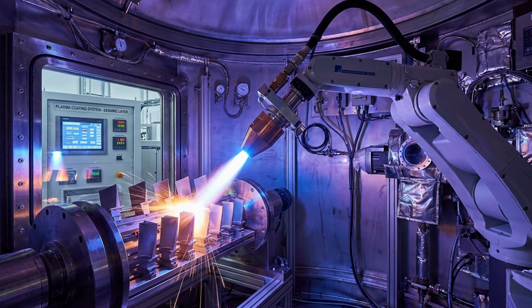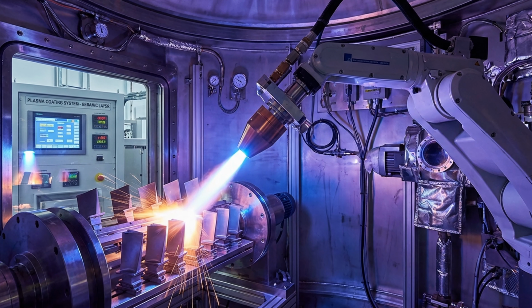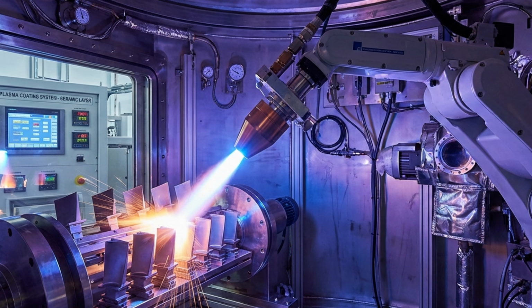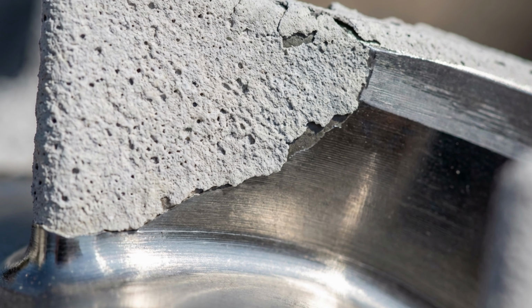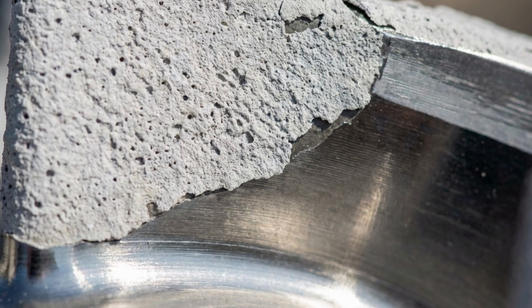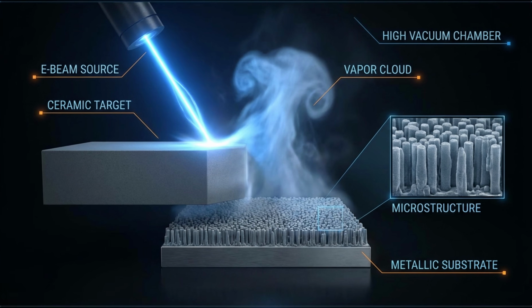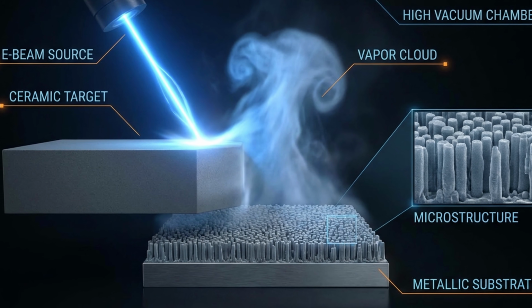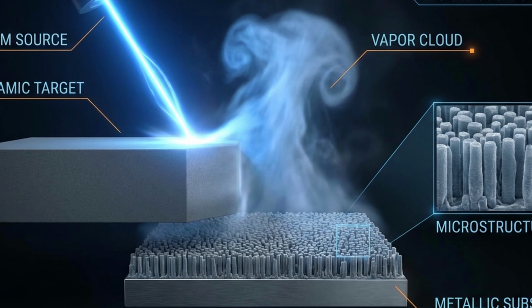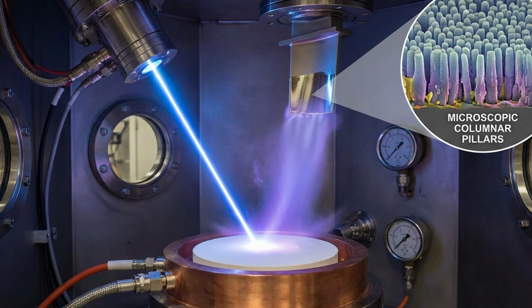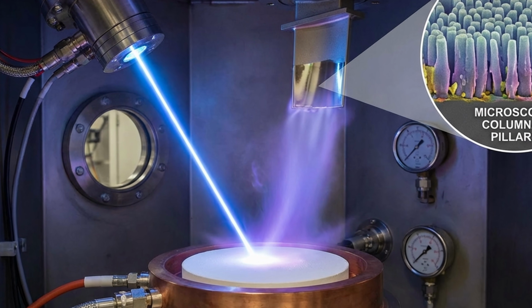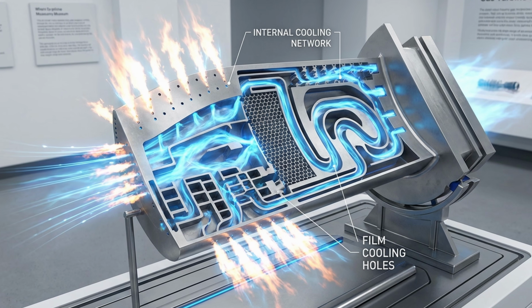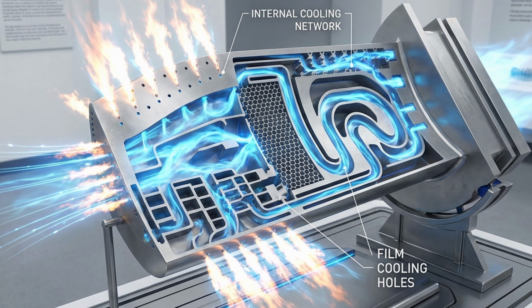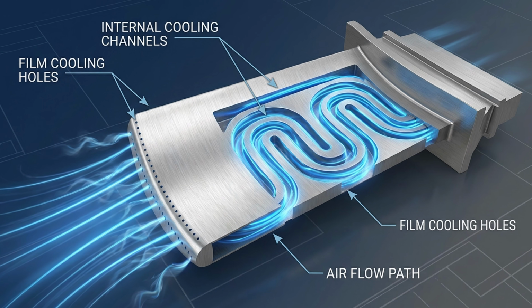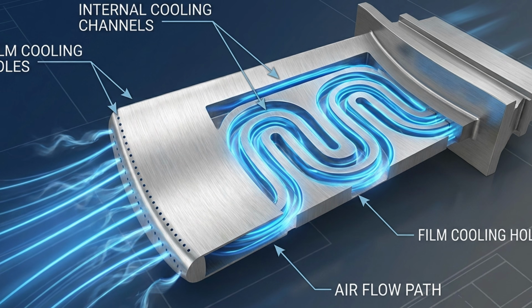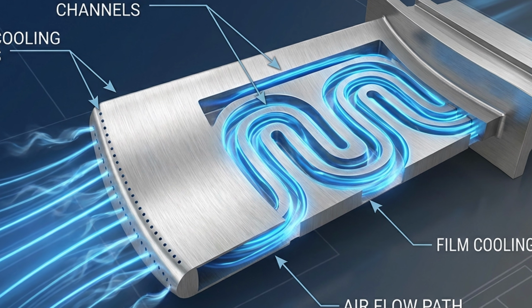To further insulate these single crystal blades from the melting heat of the high-pressure turbine, the aerospace industry developed advanced thermal barrier coatings. These microscopic ceramic layers possess extraordinarily low thermal conductivity and are applied directly to the working surface of the turbine blades. Deposited onto the blade surfaces using techniques like electron beam physical vapor deposition, which provides superior strain tolerance through a flexible columnar microstructure, or air plasma spray, these coatings are a mere fraction of a millimeter thick. Yet when combined with intricate internal cooling passages that bleed cooler air from the compressor out through microscopic holes in the blade, these thermal barrier coatings create a vital temperature drop of 100 to 300 degrees Celsius between the volatile exhaust gas and the metal surface.